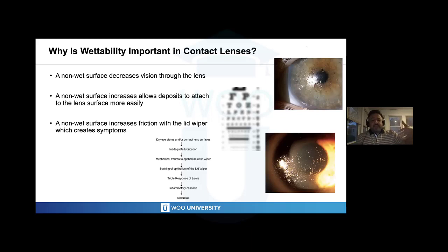And that will start the cascade of lid wiper epitheliopathy, which is really a vicious cycle because as our surface is non-wet, we increase friction, our lid wiper breaks down, our lid wiper does a poor job of distributing the tears, which creates more non-wetting, which creates more friction. And it's just this cycle that goes on. And to break that cycle of lid wiper epitheliopathy, once it really gets going, is very difficult. So a non-wet surface, other than just creating maybe the symptom that it feels a little dry, has a whole host of other ramifications which significantly affect our patient's wearing experience.